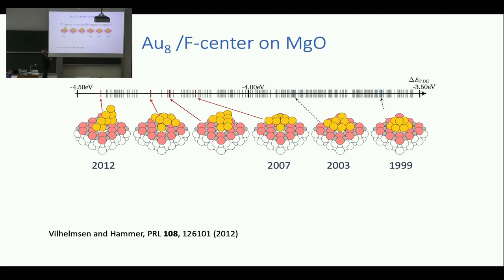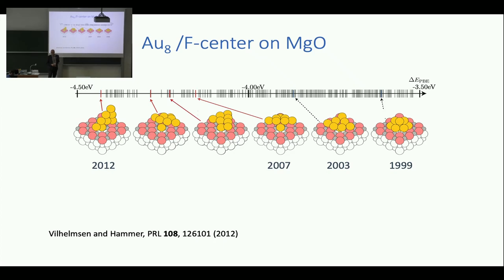Most strikingly, in this case the optimum structure we found is beyond human imagination — it's an upstanding particle. Günther is almost shaking his head: that can never be true. Probably not, because this is one exchange-correlation functional, the PBE. As soon as you apply something where there's Van der Waals interaction, all the other ones gain a little energy because they lie flat on the surface, whereas this one that stands up will suffer and will no longer be the most stable. But the question was: with the PBE functional, which is the better structure? We should have found that back at the turn of the century, had human imagination been good enough.